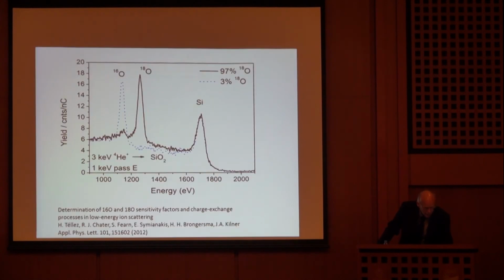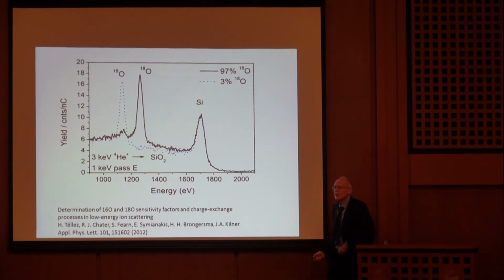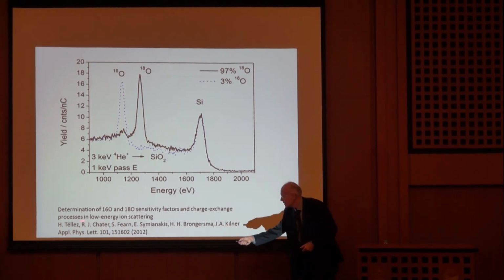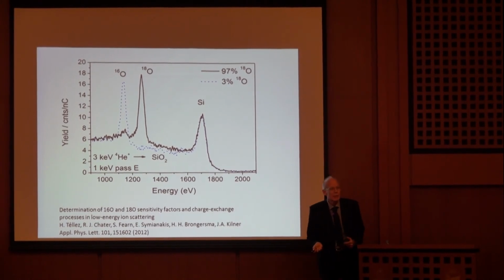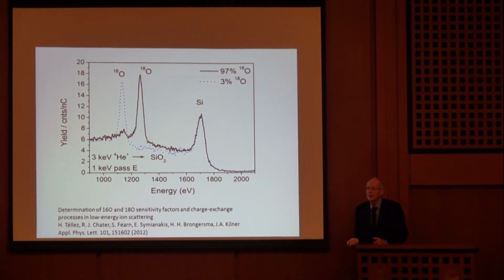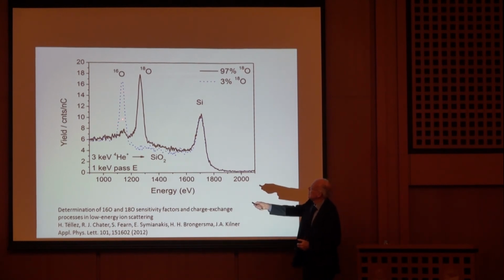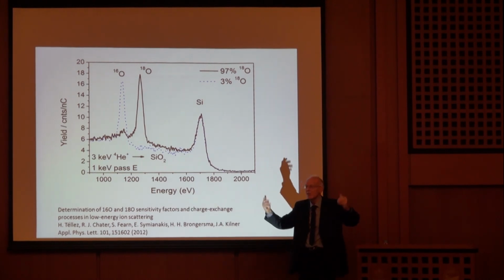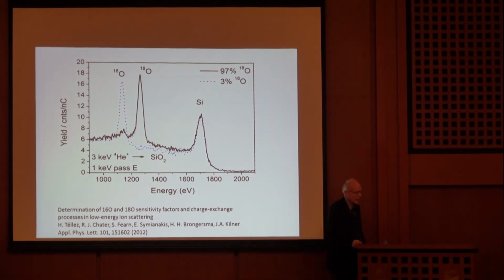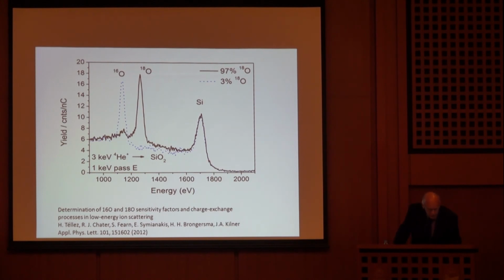Or if I go one step further, what we did is O16, O18 exchange, and that is a collaboration with the group of Professor John Kilner at Imperial College, and recently there was a very nice paper on oxygen exchange with ion scattering. You can see that you can easily separate O16 and O18. They're easy to measure and to separate, and so we use that to